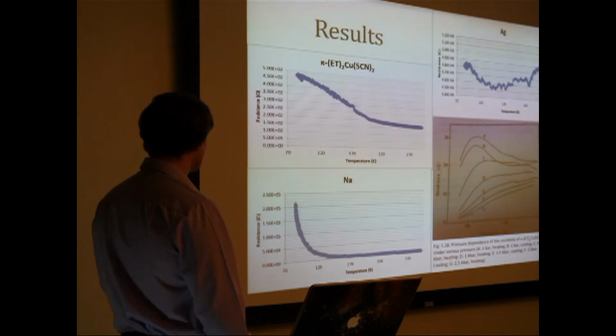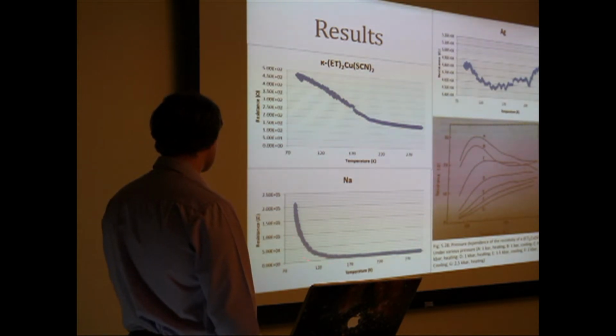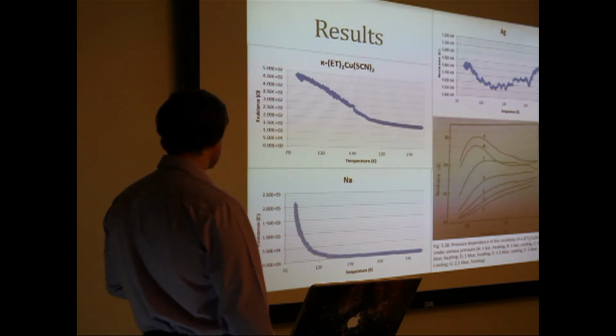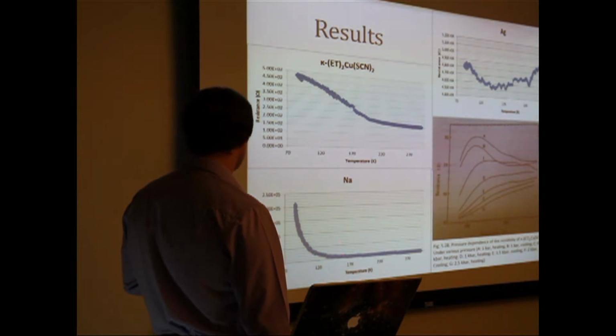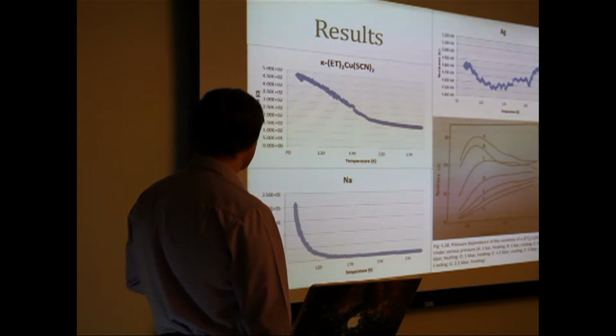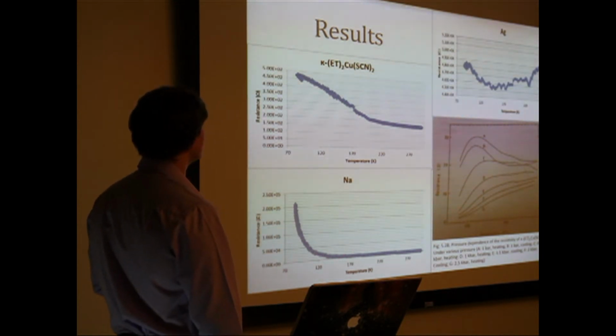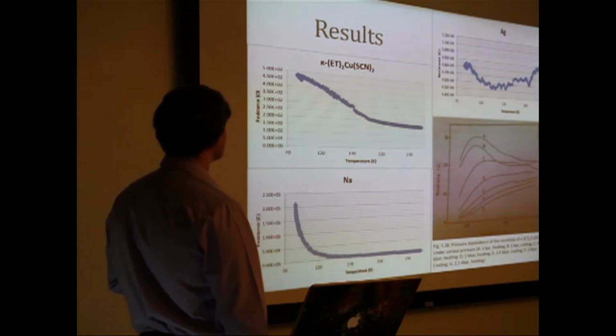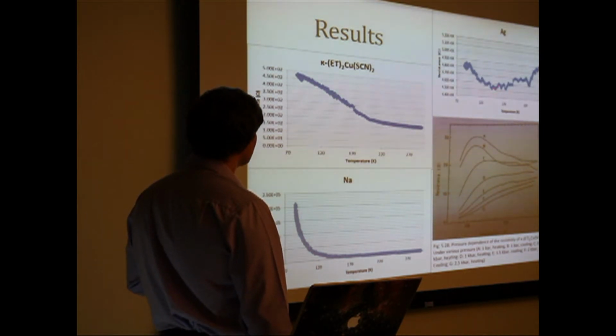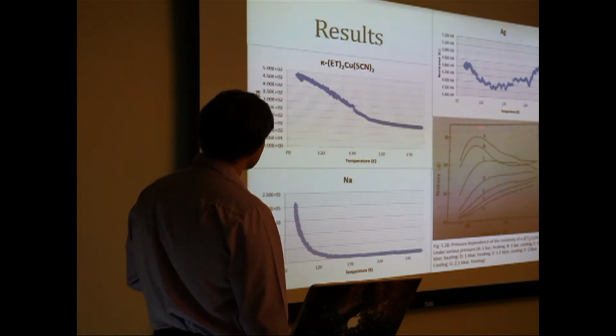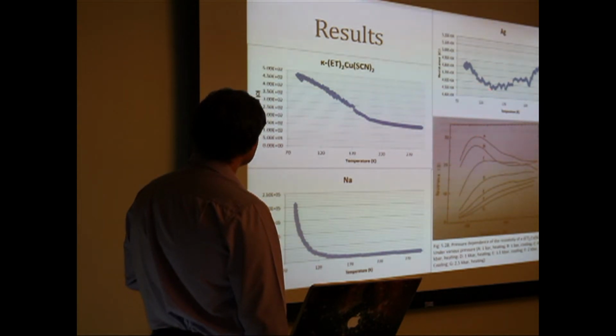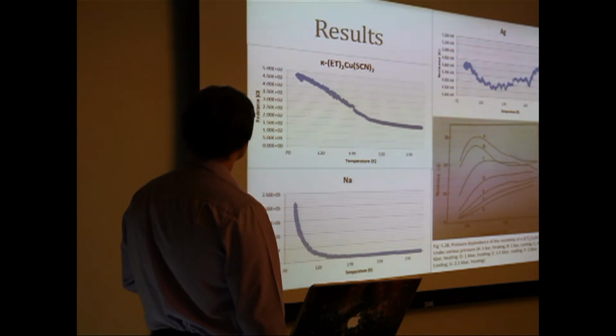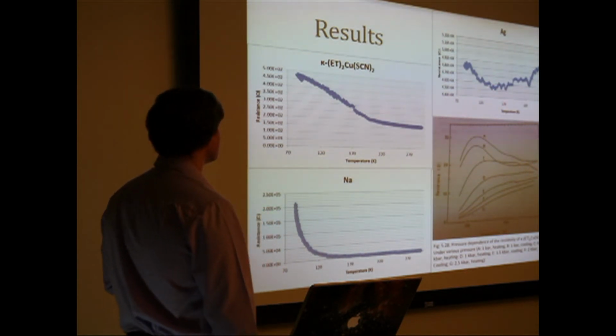As you can see, the curve is actually beautiful. It has an insulator-like property, which means that we actually did change the crystal right around here when it starts increasing. And then this one looks crazy, but it actually is good too because we actually did change it as well. Right around here, where the peak is, right here. The peak for this one is about 100 Kelvin, and this one is about 150. So that's good. It means we actually changed it.